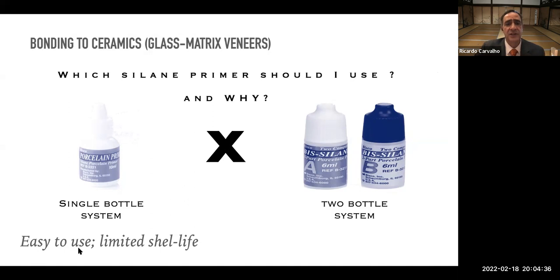Single bottles are easy to use, but they are already activated in the bottle. You probably know that silane, the way it is sold by chemical companies, is not really effective. You need some acidity in the solution in order to activate the silane and make it silanizable. And that's what happens here. In this single bottle, they have silane, they have the solvent, and they have a little bit of acid to activate the solution. And once it is activated, you have a limited shelf life.